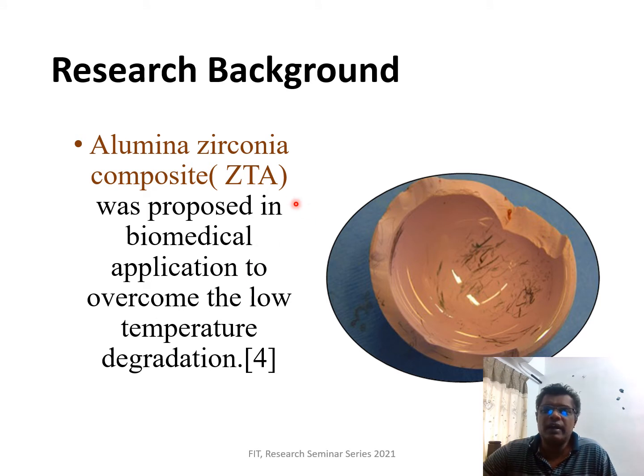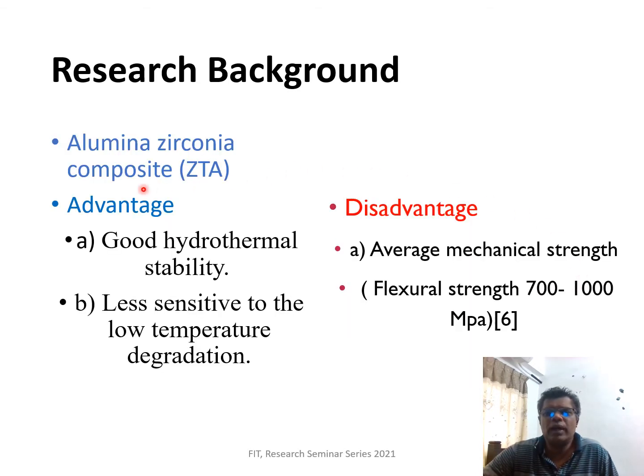Then concurrently another material was used as an alternative to zirconia. It was called alumina zirconia composite. Alumina and zirconia added together as a composite was proposed in biomedical application to overcome the low temperature degradation faced by zirconia. The advantage of alumina zirconia is very good hydrothermal stability, less sensitive to low temperature degradation. That means it does not easily become rough. The grain size does not grow as fast as yttria zirconia, so it is not prone to failure.